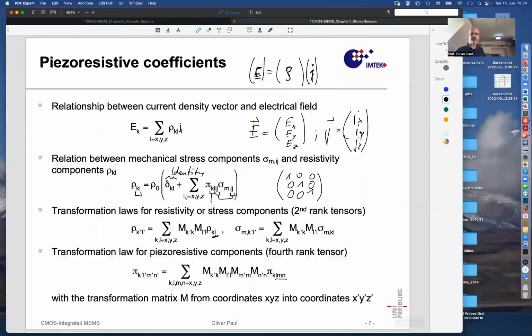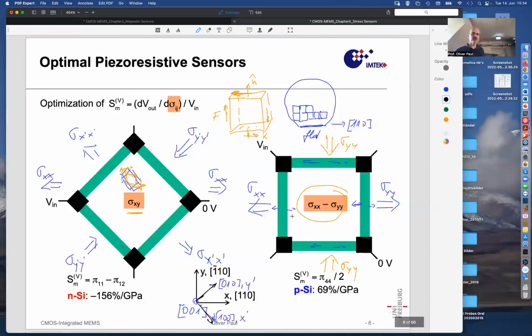So applying this formula for sigma leads naturally to this connection, that this unprimed sigma shear is equal to a difference of sigma normals in the x and y direction. And so if we look at this stress here, this must be a shear stress in the rotated coordinate system. And yes, it is the case. Shearing it, pulling it along and squeezing it from the top, is the same as shearing it in a coordinate system that is under 45 degrees, and then you obtain the same effect.